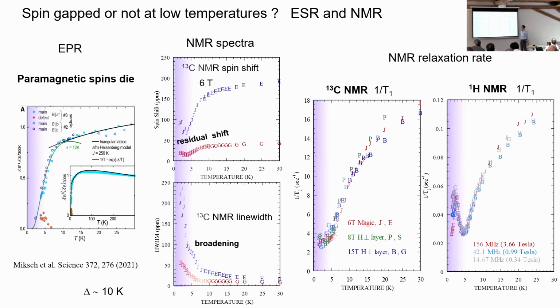But I want to say that in these materials, the form factor has nearly no Q dependence. Please consider one molecule here. In the copper oxide, if you see the copper nucleus here, and in the neighboring site the copper spins are, for example, in these directions, this copper site shows a very large internal field.